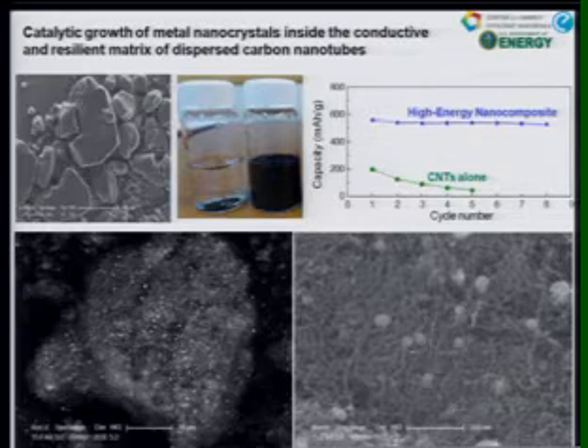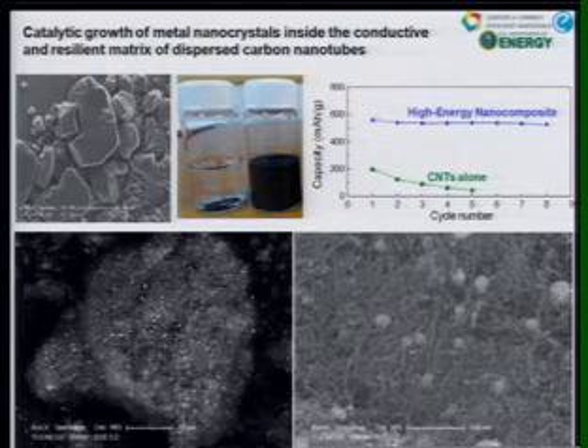Compare the performance to the carbon nanotubes alone. Interestingly, in this high resolution electron micrograph, you can see the evidence of what we are discovering seems to be an atomic level tethering, the bonding between the carbon nanotubes and the nanocrystalline tin. Perhaps, we suspect, explaining to some extent the high power of this material.